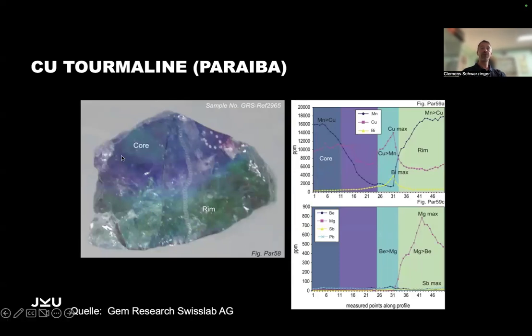So this is more what people associate with this Paraiba color, this bluish color. And you see that here in the core, you have manganese and copper. Copper makes it this bright Windex blue. Manganese is a pink chromophore. And so you see here this stripe of perfect blue color. This is where you have the maximum concentration of copper. You have more copper than manganese. And again, then manganese and copper in various concentrations, giving you all these different colors.